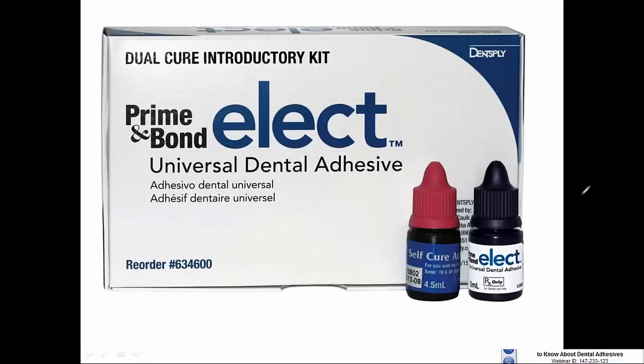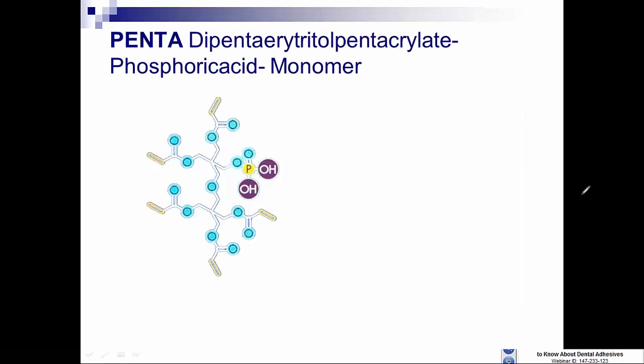So this would be Prime and Bond Elect, and as I just mentioned, it can be used for indirect restorations. It has an extremely low film thickness. So Prime and Bond Elect is ideal for indirect crowns, inlays, and onlays because its film thickness is very low and will not inhibit seating. But when using a dual cure resin cement, the self-cure activator must be mixed with that resin cement. Now, Prime and Bond contains a phosphoric acid monomer,